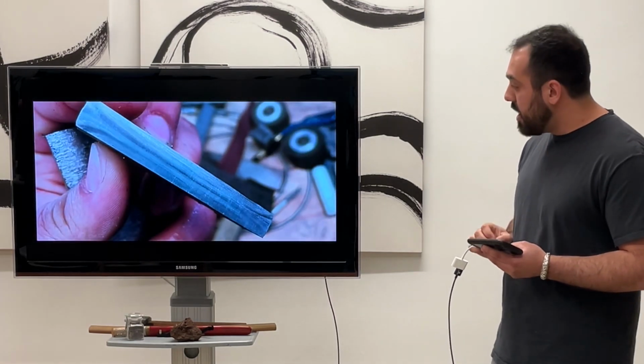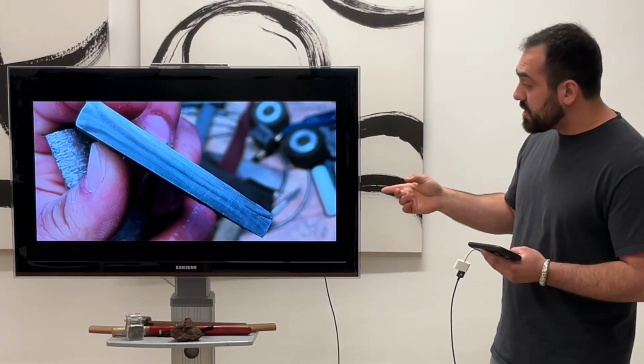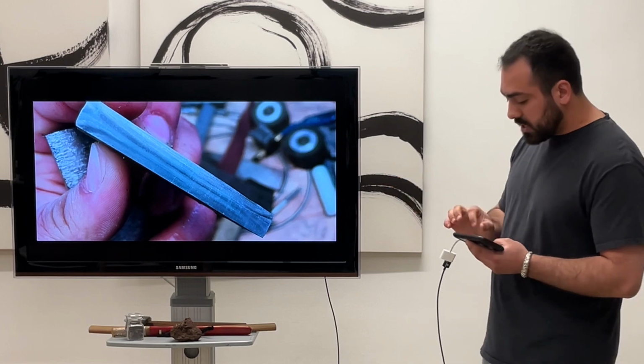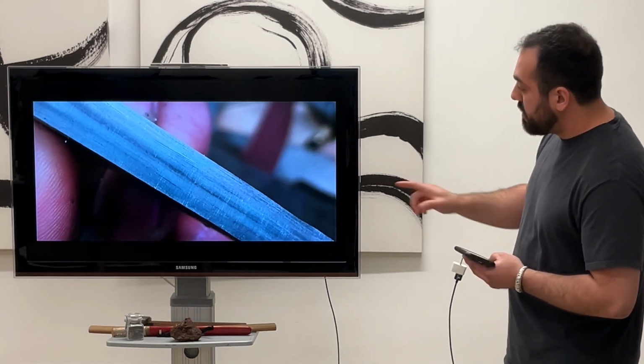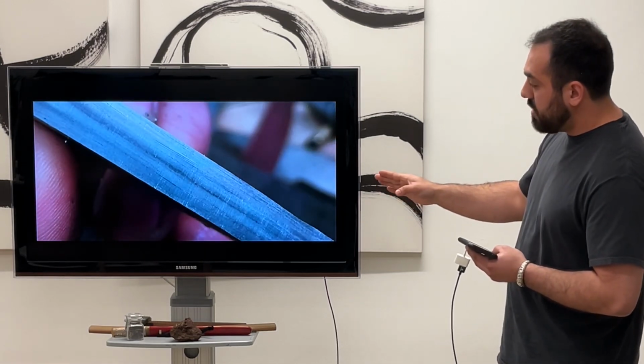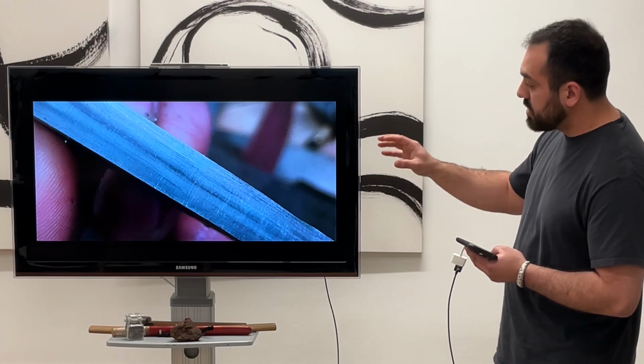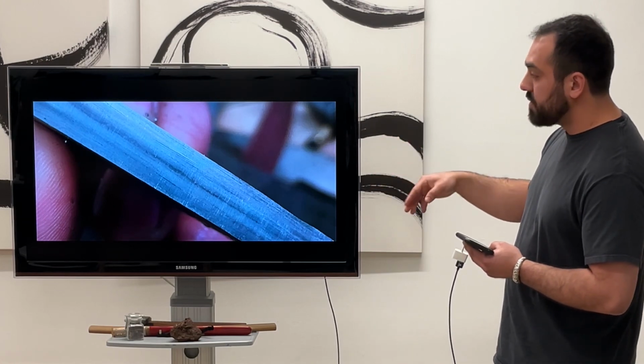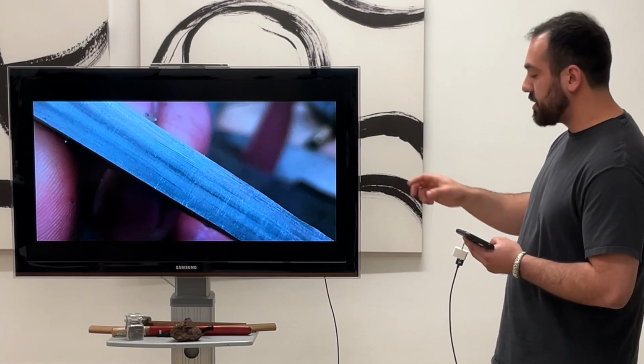This is a cut and etched section of this material after 5 folds. You can see the stringy inclusions that are left in the material still. The darker sections are also differences in carbon coming out in the etch.